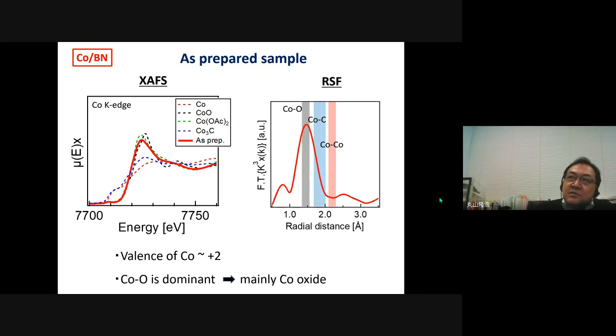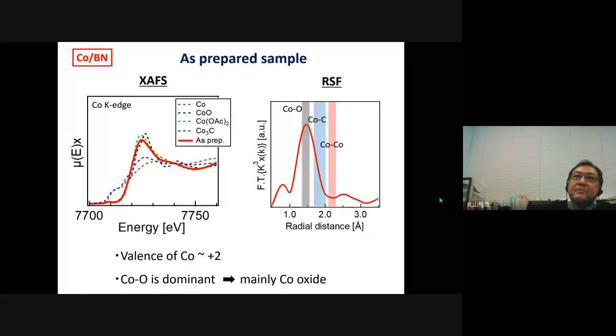The right figure is RSF, radial structure function. The cobalt-oxygen peak is dominant. This confirms the as-prepared sample was mainly composed of cobalt oxide. Next slide, please.